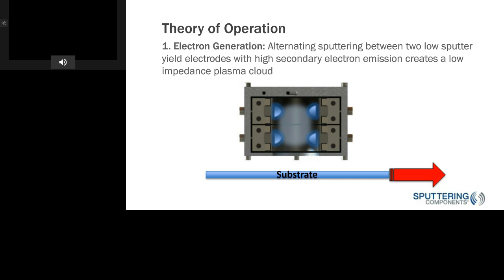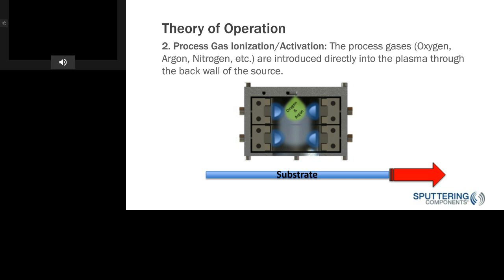In stage 2, the process gas ionization activation, the process gases that I mentioned already, oxygen, argon, nitrogen, are introduced through that manifold that I talked about directly into the plasma through the back wall of the source. So that then mixes into that cavity.